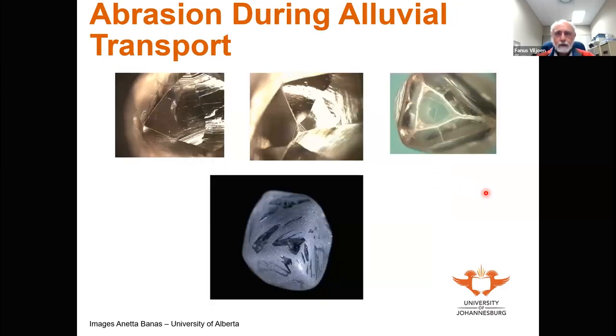And then finally, in terms of transport, if your diamonds are eroded out of the kimberlite and end up in the alluvial environment, initial transport will show up as points and sharpest edges abrasion, with an increase in abrasion, which could or might be due to an increase in distance from the primary source. You see more abrasion, which becomes progressively more pronounced, as you can see here, until eventually, with distal transport, you have these ground down surfaces,